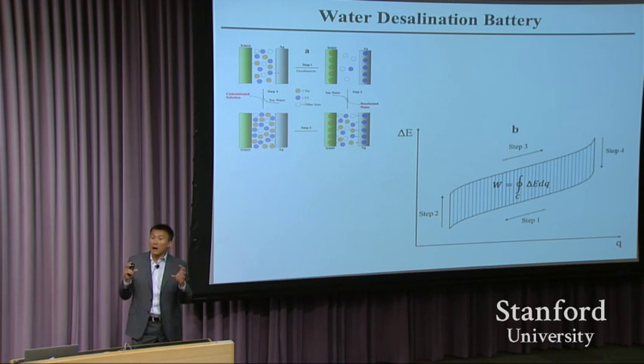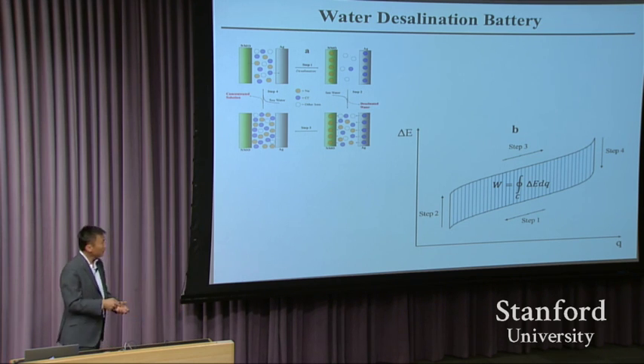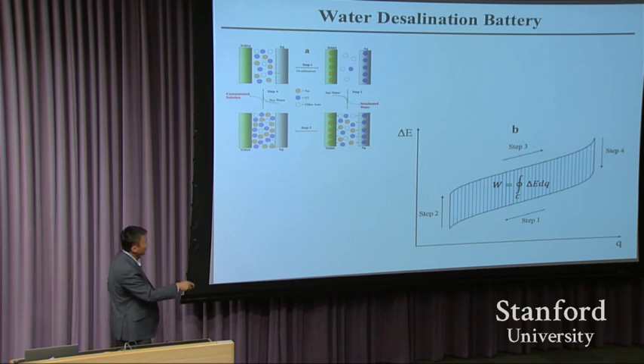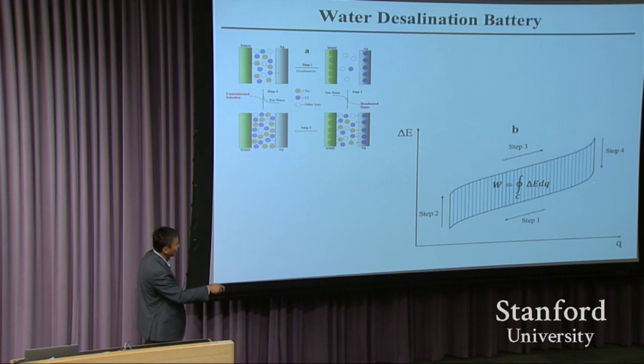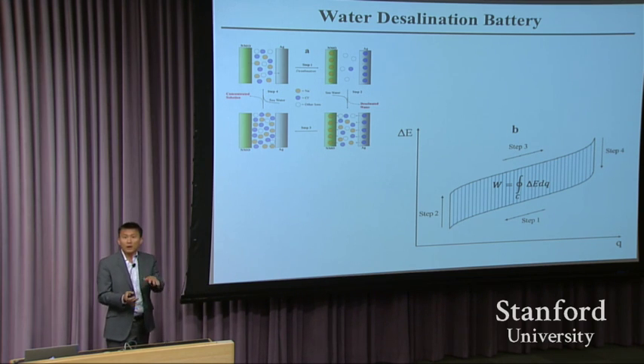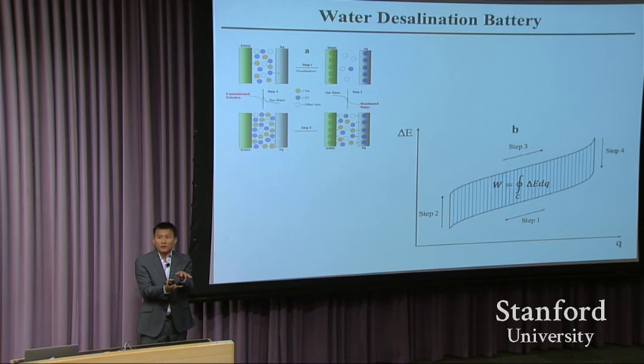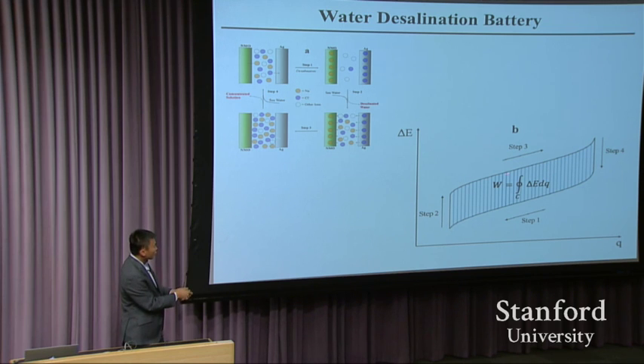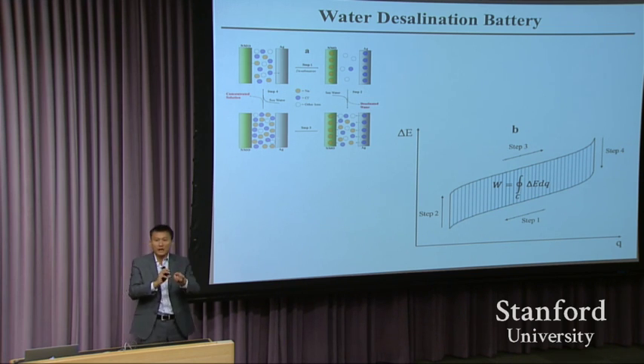really produces the amount of energy you need to put in to do water desalination. Okay? This is really close to the thermodynamic limit. The difference between the voltage right here on the top and the voltage at the bottom is defined by the thermodynamic potential depending on different concentrations of the salt. At the higher concentration, the voltage curve is on the top. At the low concentration, the voltage curve is at the bottom, plus some of the kinetic loss during this process.